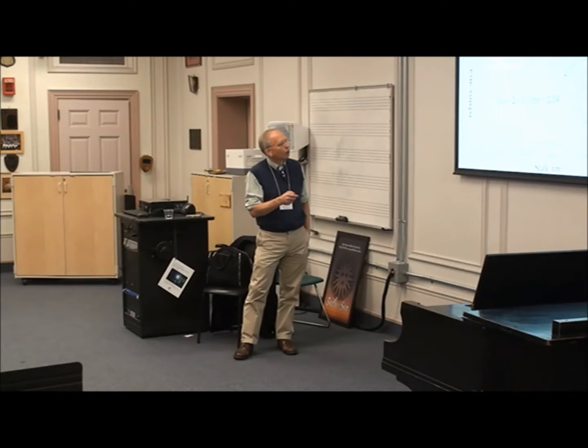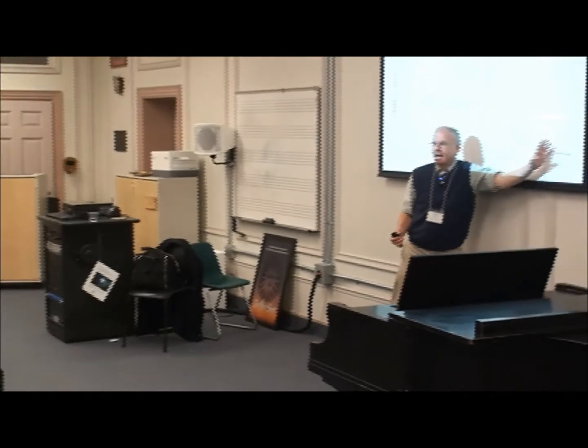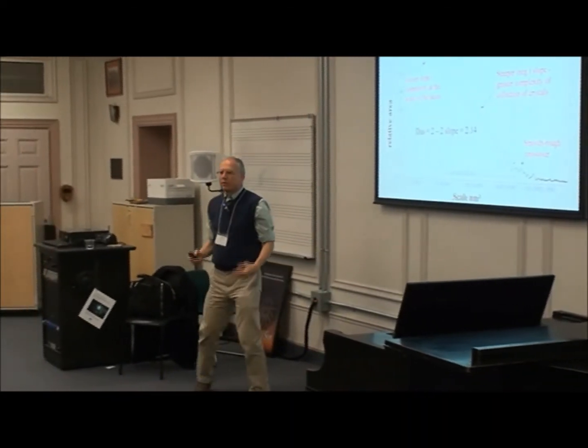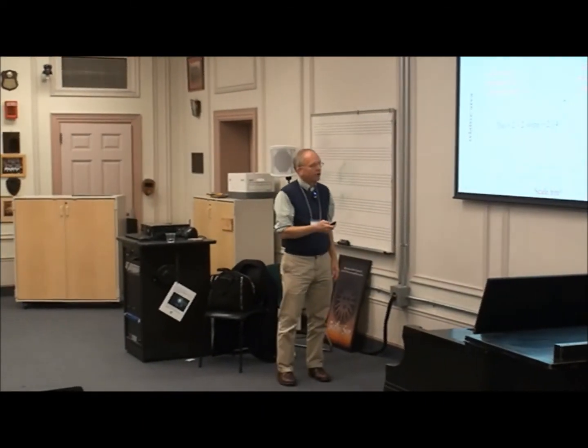So the 4,000 square nanometers is 1, 2, 3, 4 is about here, and you can see that's already in this range where we're looking at the geometry of the facets. And here we're looking at the geometry of this collection of crystals. So we have a kind of decomposition here already. Here's the smooth scales, here's the scale of the jumble of crystals, and here's the scale of the facets. And so we've got three different kinds of geometric character that we can look at there.